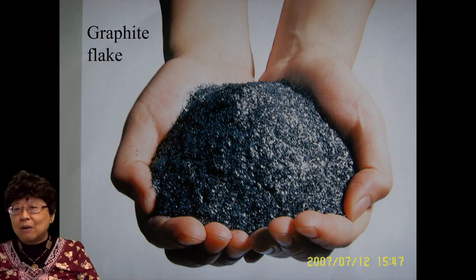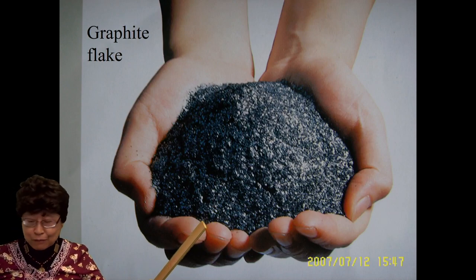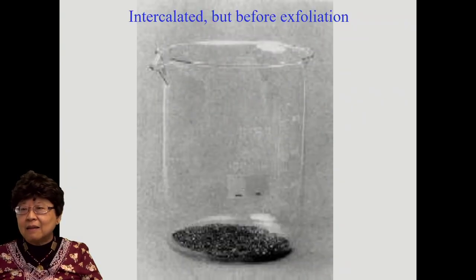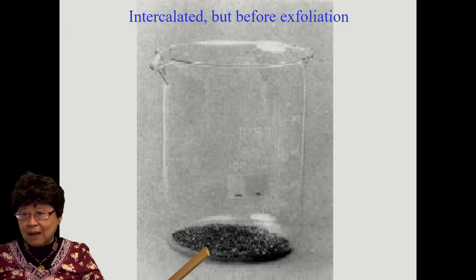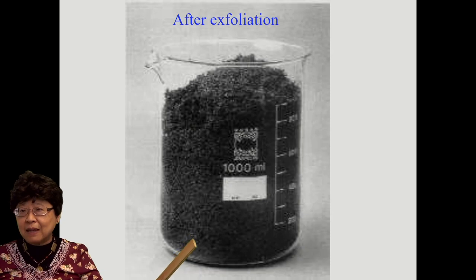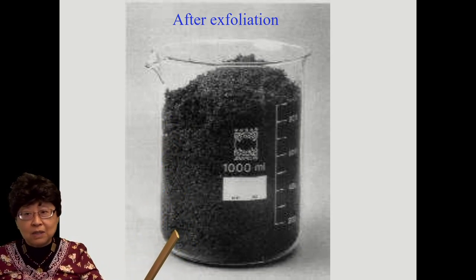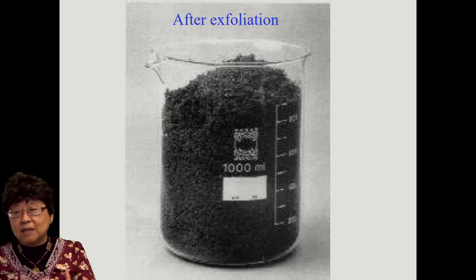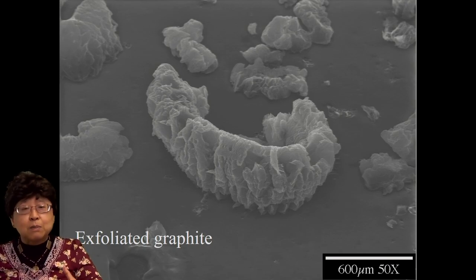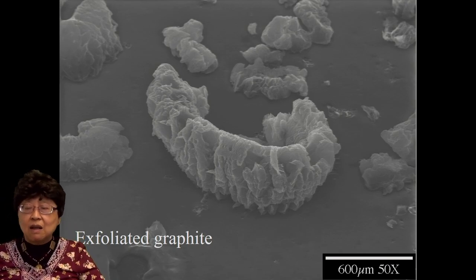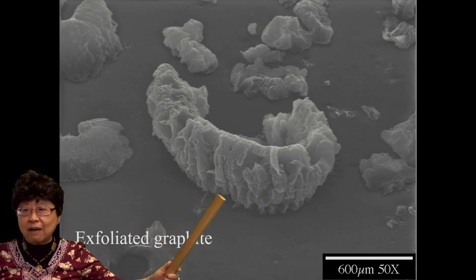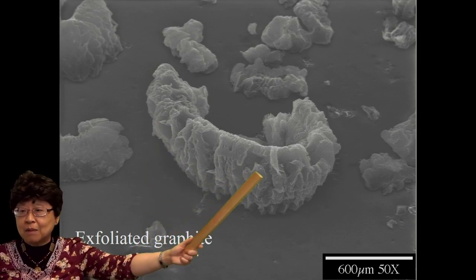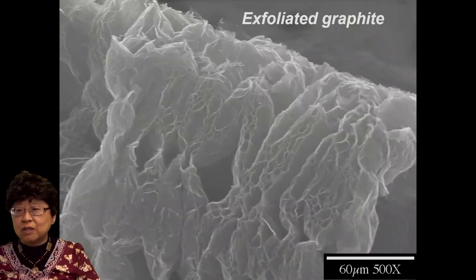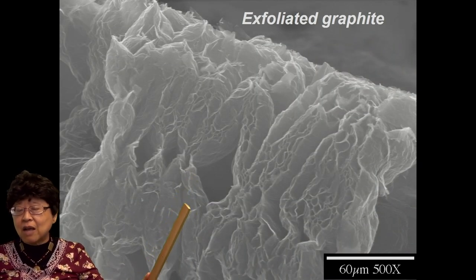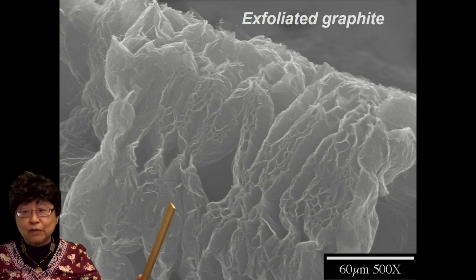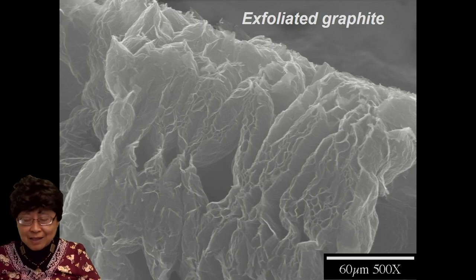Okay? Now, this is graphite flake, which can be mined from the ground. And you can intercalate the graphite flakes, and then suddenly heat that rapidly, and it puffs up. And we call that puffing up exfoliation. And the exfoliation is because the intercalate wants to expand or vaporize, and thus there's a ballooning action. And this is the exfoliated graphite. One flake has become looking like a worm, having a cellular structure. And you can see the cellular structure. As a result of that structure, you have a lot of surface area per unit volume. And that helps the shielding.